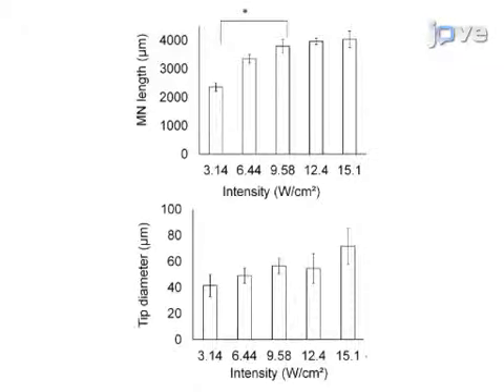The effect of UV intensity on the microneedle length and tip diameter was studied by varying the intensity of the UV light from 3.14 to 15.1 watts per square centimeter at a constant focal length and light source distance. It was found that the average microneedle length and tip diameter increased with increasing intensity.